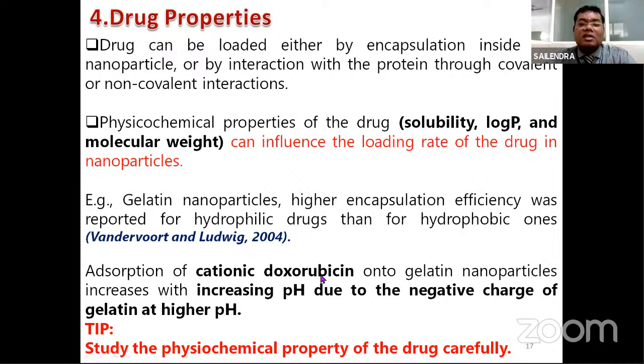Also, the charge on the drug molecule is very, very important, in terms of how it is going to interact with the protein nanoparticle surface. For example, you have cationic doxorubicin, and if you want to load it on gelatin nanoparticles, loading increases with increasing pH due to the increase of the negative charge of gelatin at higher pH. So at higher pH, you will have more of this negative charge, and it is going to attract this cationic doxorubicin on its surface, and there will be a perfect attachment of the drug molecule and the protein nanoparticle.